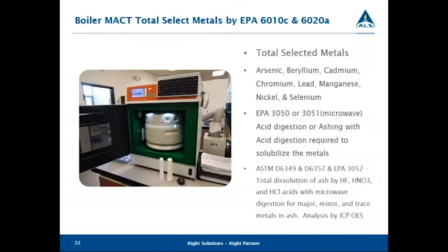Some other tests that we can perform on the samples are actual fuel analysis for heavy metals. And those typically involve doing a total dissolution of the ash material using HF, nitric acid, and hydrochloric acid with a microwave digestion system. The microwave is shown in the picture there. And the metals that we do for these methods are called major, minor, and trace metals in ash. And analysis is by ICP OES.